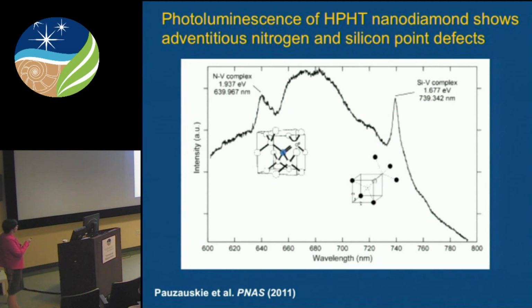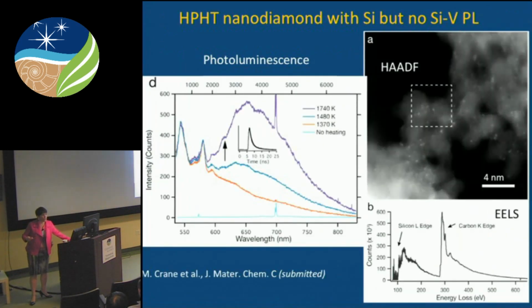So as they increase the pressure and increase the temperature using the laser, they can preserve the porosity intrinsic to the aerogel, but get the high pressure structure of diamond. I've been able to help them confirm that they have, in fact, nanodiamonds. Their early studies showed that they had adventitious nitrogen and silicon, giving them luminescence.